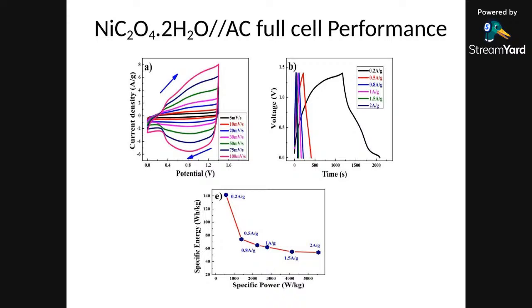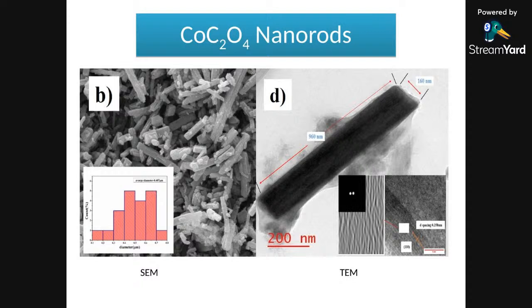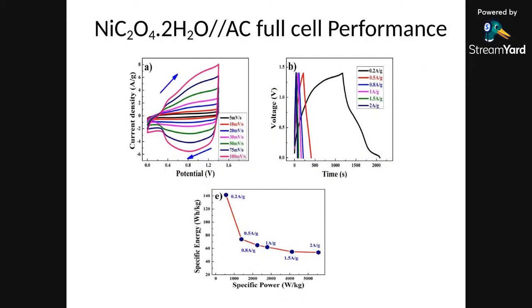So that's why there is a redox voltage coming around above 1 volt during the charge and around 0.7 volt during the discharge. So we are able to get moderately high energy and high capacitance performance, and at around 0.2 ampere per gram current density, the energy was close to 140 watt hour per kg, and the power was close to 800 watt per kg. And if you go to 2 ampere per gram, which is a very high current rate, then also we can get around 60 watt hour per kg energy density, and more than 5500 watt per kg power density.